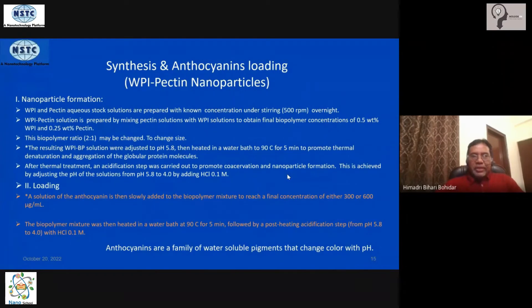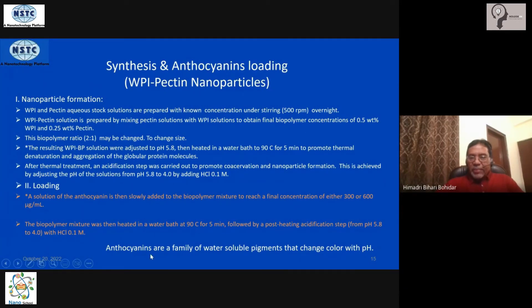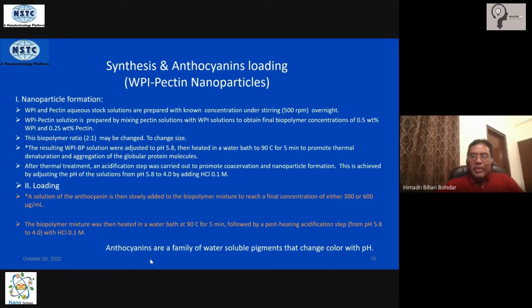If you want to incorporate a drug into the nanoparticle, this is the stage to add it — after mixing but just before heating begins. Add the drug at the right concentration and then follow the rest of the procedure. In this particular example, the encapsulated molecule is anthocyanin — a water-soluble pigment whose color changes with pH — encapsulated within this protein–polysaccharide nanoparticle.